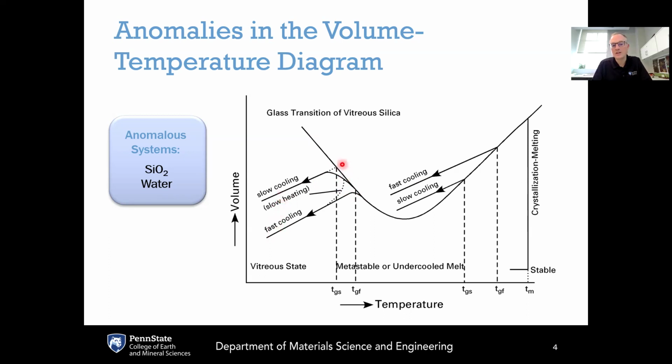And this all goes back to the anomalous behavior of the supercooled liquid state. Like I said, silica behaves the same way. So you can quench silica in a regime that has the normal behavior on the right-hand side, or quench silica in this anomalous, slower regime, which flips the order of the molar volume versus cooling rate.